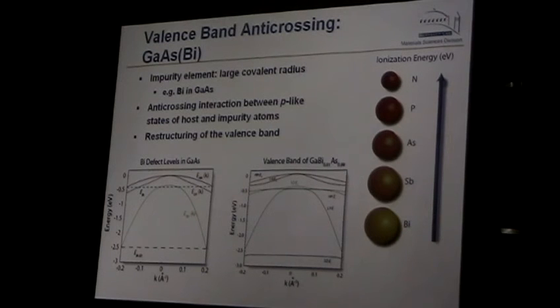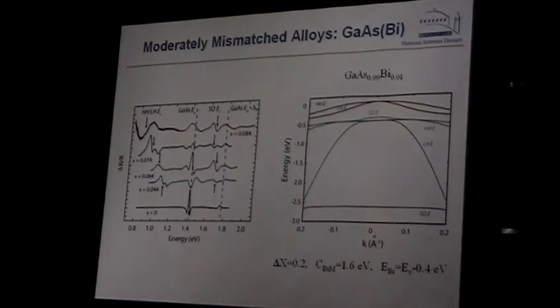The problem here is much more complicated because this is a 6-fold degenerate system, so the interaction is complicated. But basically, the overall result is that we form one band here and the other band here. So it cuts the valence band into pieces. We did a lot of studies of this system because it is interesting for some light-emitting diode applications because it has less change of the band gap with temperature. And we found that it behaves as expected.